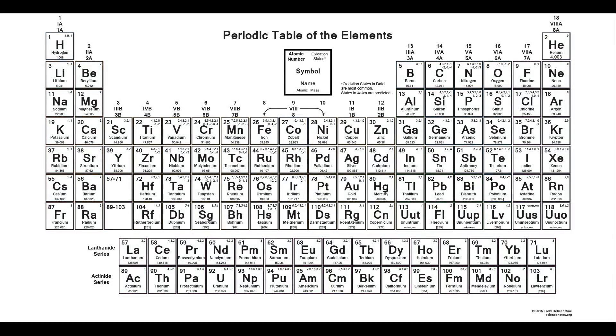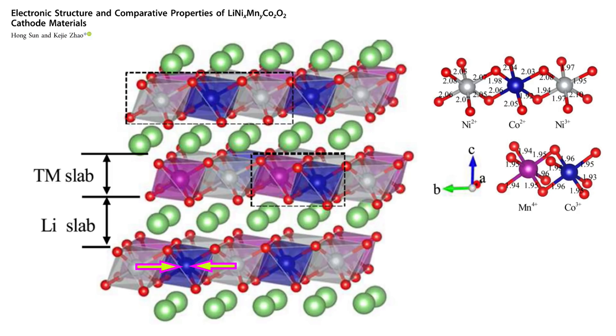I've heard it stated that Cobalt stabilizes the cathode, but my view is that this is a partial explanation. There are half a dozen other elements that can dope a cathode for structure besides Cobalt. However, Cobalt has a rare set of characteristics — it both forms a strong backbone and stores energy. Other elements that can strengthen the backbone, like magnesium, hold the crystal structure strongly but also grab lithium ions and don't allow them to enter and exit, resulting in lower energy density.